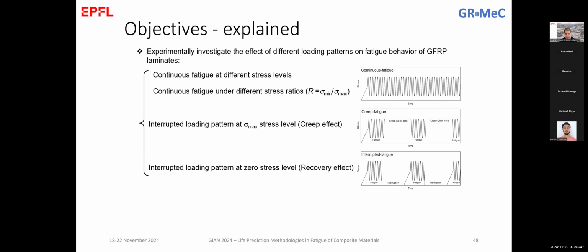In all these cases, as we mentioned, we kept the specimen in the machine. We did not remove the specimen to avoid what we discussed also yesterday, the effect of the gripping pressure, the alignment of the specimen, and so on. So we then studied the mechanisms developed under the different loading patterns to be able to correlate the observed phenomena to, let's say, the physics of the failure.